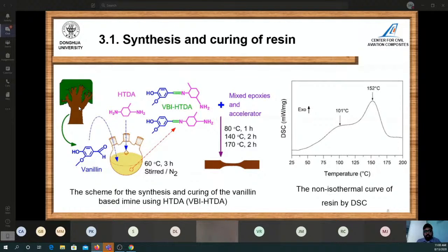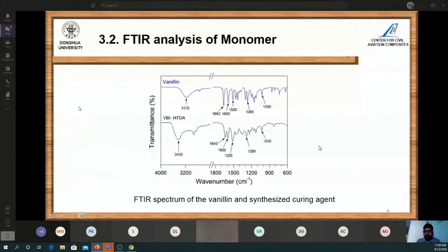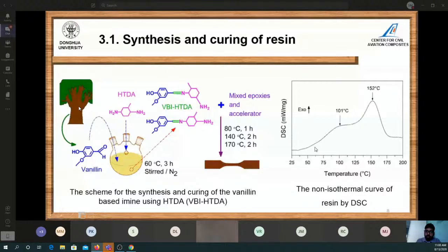And then we reacted with mixed epoxy, like mixture epoxy, diluent epoxy, to get the coupon, and the curing scheme is also presented here. 80 degrees centigrade for 1 hour, 140 degrees centigrade for 2 hours, and 170 degrees centigrade for 2 hours. So here are the curing peak and curing temperature for this, that how much temperature should be given to cure this reaction.